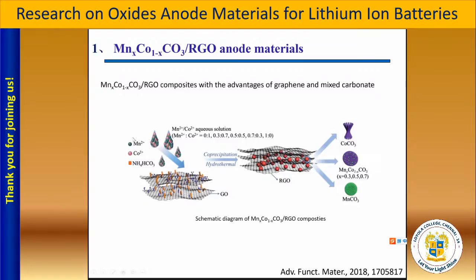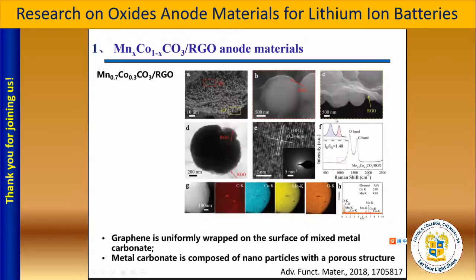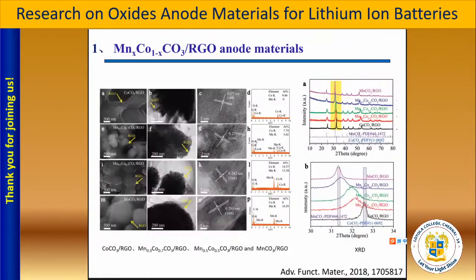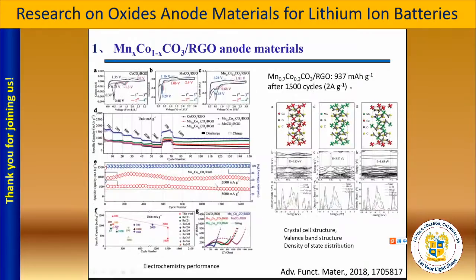It will be in the material with manganese ion, and we can adjust the content of the cobalt ion and get different materials. It could be cobalt carbonate or manganese carbonate, or when we adjust the ratio of the manganese ion and the cobalt ion, we can get double metal carbonate. It's very interesting because we can see some microstructure and better electrochemical performance. This is the first kind of material.